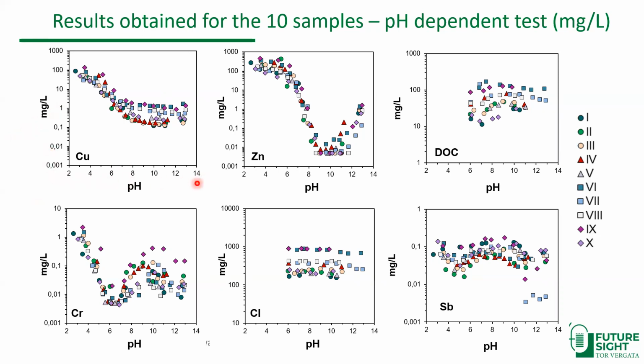So we find solubility curves that may vary very significantly with pH, by various orders of magnitude, as we well know for zinc, lead, for example, but even chromium. Chromium has a typical shape related to chromium-6. Then we see instead that chlorides don't change particularly with pH, and we see the samples that leach more. It is interesting to note that also for antimony, the shape of the curve is quite similar for most samples, except for sample 7, where cement is added.